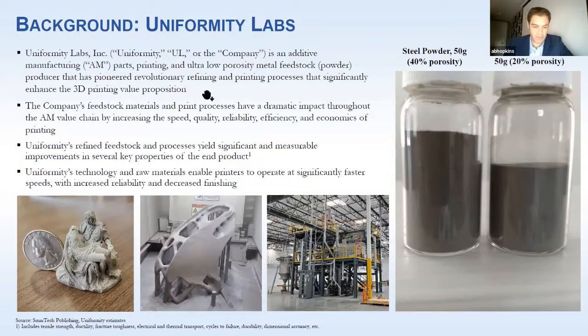the feedstock and changing the parameters in laser powder bed fusion, you can enact rather substantial changes. In fact, you can, for example, print with 2 to 3 times the throughput without changing laser power. You have to change laser speed, scan a little bit faster if you want to print faster. But then the result is the physics can be modified to achieve more reliability, less residual stress in the process, faster printing, things that the industry needs.